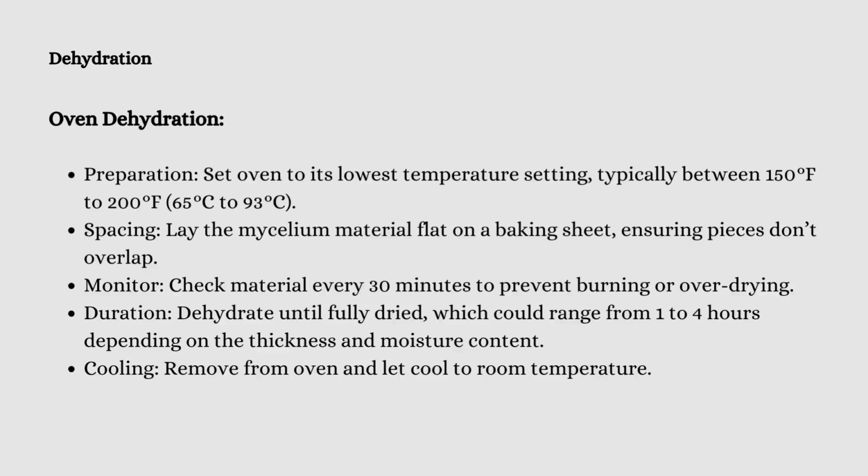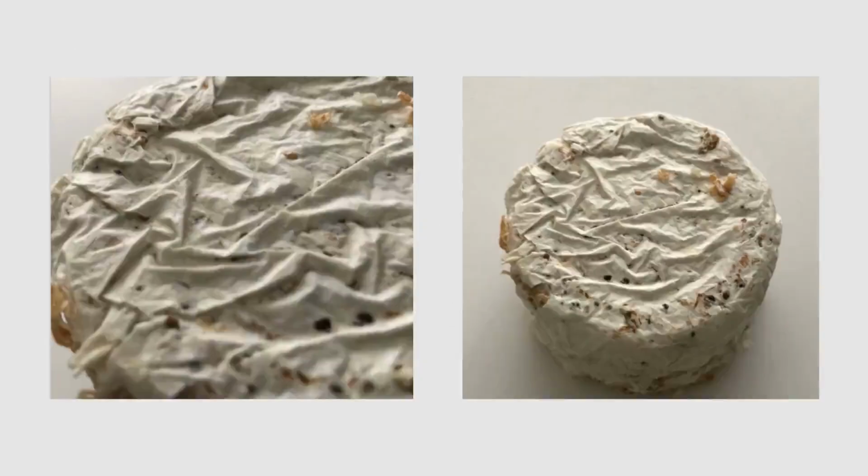And depending on the thickness and the moisture content, again, this could take like 1 to 4 hours at that temperature. Then, once you are content with the level of dehydration, you're going to remove it and let it cool at room temperature. Easy enough.